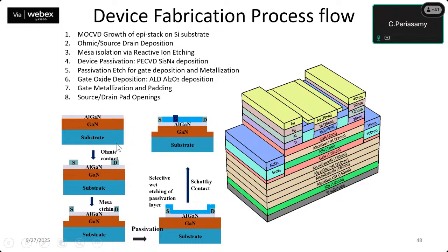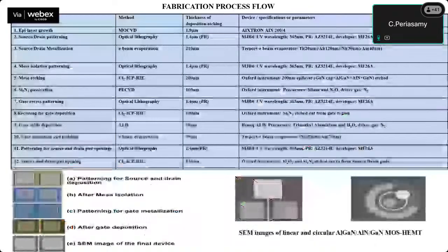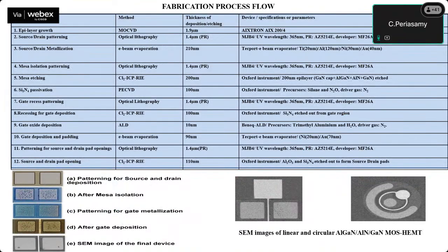Okay, so these are the details. First we have deposited the ohmic contact. So this is the full detail of the fabrication for this proposed structure. As I already told, we have grown gallium nitride on the selected substrate by using the MOCVD technique. Metal organic chemical vapor deposition is the best method to grow epitaxial layers on the selected substrate. Here we have chosen silicon substrate. One can choose silicon or sapphire substrate.